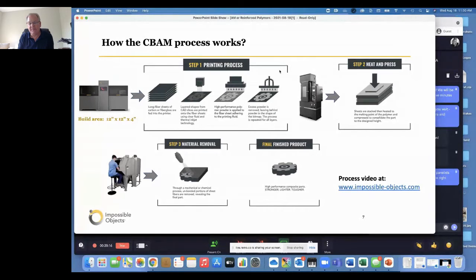and that will stick to where the wetting fluid was placed onto the fiber sheet. The next step is that all excess powder is blown and vacuumed off. This is all done at room temperature, so there are no thermal effects on any of the thermoplastic matrix materials. The sheets are automatically stacked, and that completes the printing process.